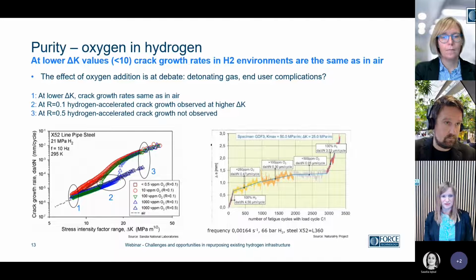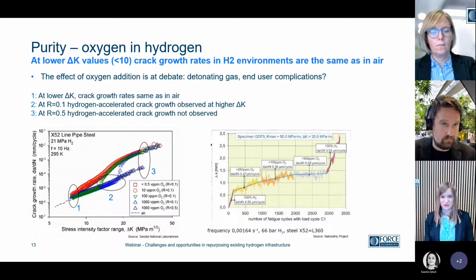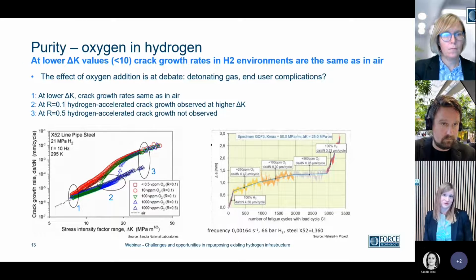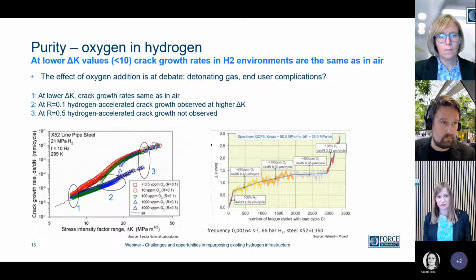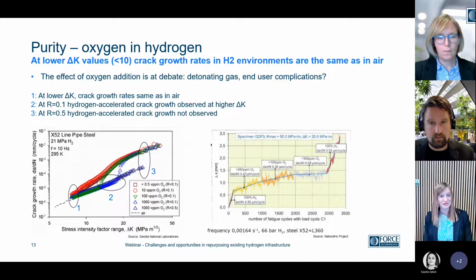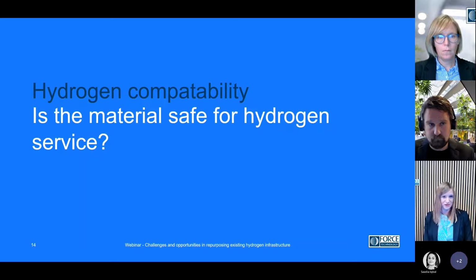The same goes for this study where oxygen is supplied in this horizontal part of the curve, and as oxygen is removed and we go to 100% hydrogen, we see a steep uptake. That's just examples. But in the context of repurposing, this is very important, because if we have a pipeline with an oxide layer from corrosion, years of exposure, it may actually inhibit the hydrogen uptake in the pipeline. So an old pipeline could be beneficial.